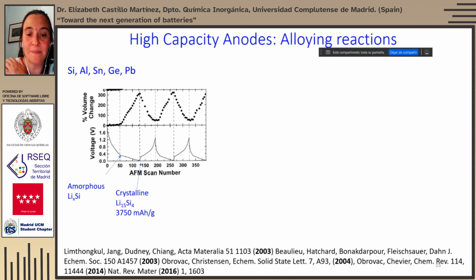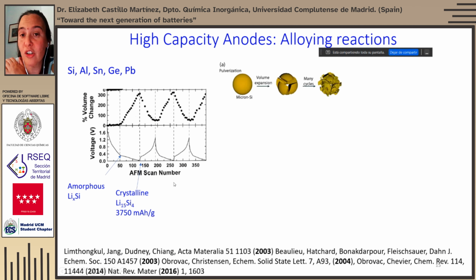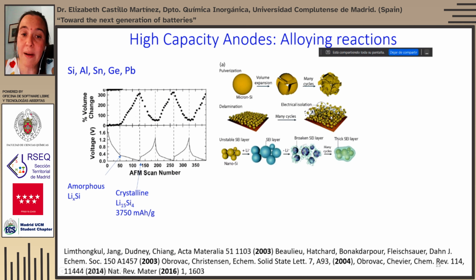that of graphite. However, as you can imagine, if almost 4 lithium atoms per silicon atom enter into the structure, there is a large volume expansion with cracking of the particles, and after many cycles, these particles get completely pulverized. Not only this happens to each individual particle, but also the SEI layer that forms on top of the particles during the decomposition of the electrolyte in the first discharge also get broken. And in the subsequent cycles, new SEI layer needs to form on the surface of the new particle. Therefore, a very thick SEI layer that then prevents a proper lithium-ion diffusion gets to be formed.